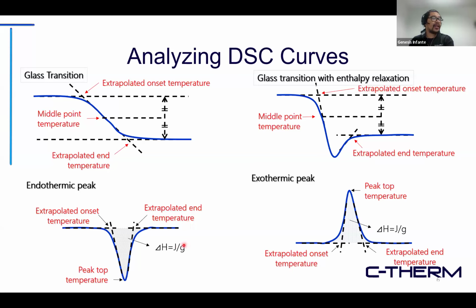Another piece of information that we can gather is the area under these curves, which is typically referred to as the enthalpy energies. So this would be something like the energy of the melt. So integration under that line or that curve corresponds to the energy associated with that particular event. The same applies with an exothermic event, like a crystallization or a reactive event like an oxidation, where you're going to have the release of energy, and that energy is characterized by the area under this curve.